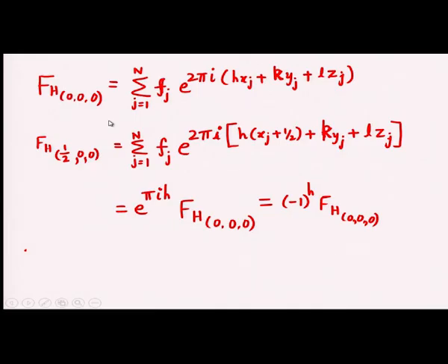So, this is how we can do the phase calculation by hand. Once you know everything, you can calculate the E map. The modulus comes from your experiment, only phases are unknown, and phases come by hand propagation. I know modulus and phase, so we can calculate the E map and get the structure.